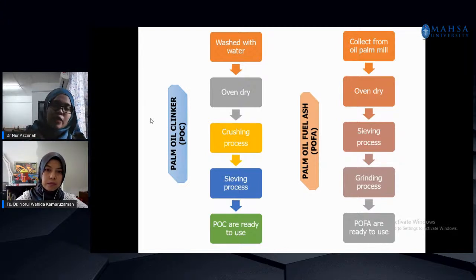For me, last time I crushed it and then sieved using a 10 millimeter sieve. Whatever passed the 10 millimeter sieve and was retained at 5 millimeter, I took and used to replace inside my concrete. For the palm oil fuel ash, I use the same method as for the oil palm shell. You have to oven dry, sieve using a 300 micrometer sieve, and then grind for 30,000 cycles. Then only can you use it.